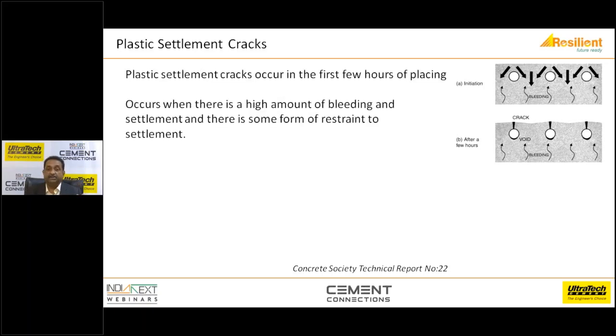This can be easily prevented by, one, a good cohesive mix. Secondly, revibrating the concrete before the concrete is set, because you can disturb the cracking pattern, and then you can overcome the plastic settlement crack.